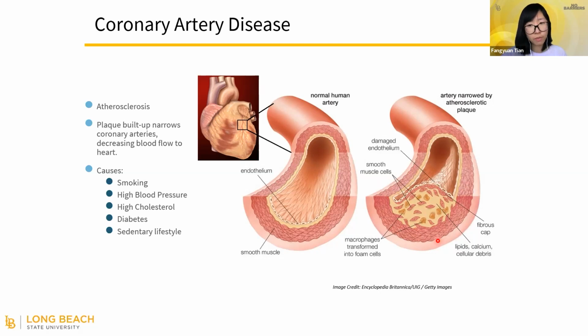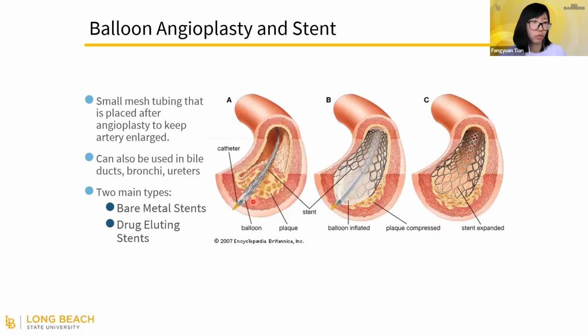Very likely 50% of the patients who suffer from this will go through balloon angioplasty surgery with a stent planted inside of their artery. This surgery is done using a catheter, a balloon, and a stent. The catheter will be inserted through the peripheral arteries on the arms or the legs of the patients. And when they reach the injured area, the balloon will be inflated to expand the stent to push the plaque back. After that, they will deflate the balloon, take it out with the catheter, but leave the stent in